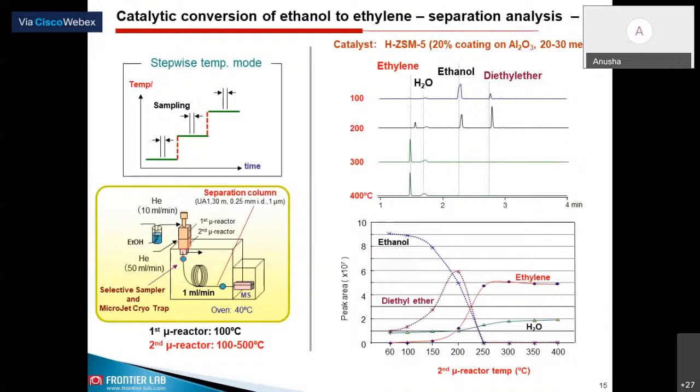Can you see the right side bottom part I'm talking about? There you can see after 230, the water became the byproduct because that's what is getting eluted, and also ethylene is getting eluted after that. So it can be clearly said that about 250 to 300 would be the optimum reactor temperature for the conversion of ethanol to ethylene using this